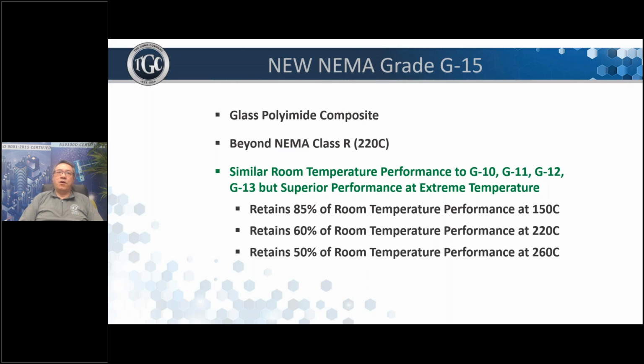G15, this is the polyimide, very expensive material, but it outperforms any of the glass grades at extreme temperature. Look at it. Class R is 220 degrees C. It retains 60% of the room temperature performance when you test the material at 220 degrees C. And it retains half of its room temperature performance at 260 degrees C. And that's indeed a very high temperature.